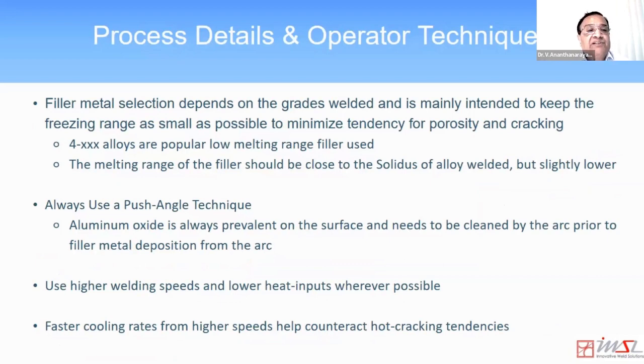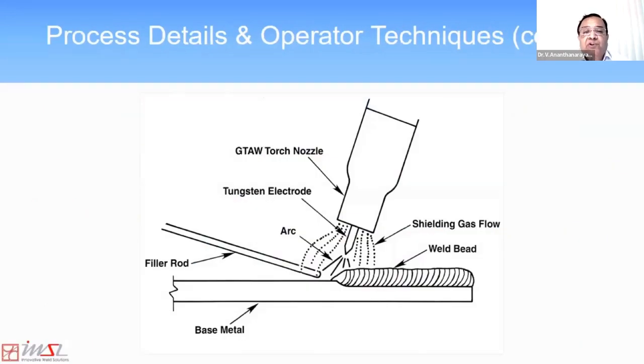And while welding aluminum, it is always necessary to use a push angle technique. A pull angle technique does not work with aluminum because of the oxide issue that I talked about. There is a need for the plasma to clean the metal ahead of the arc as you proceed. So a push angle is always essential, whether you do gas tungsten arc welding or gas metal arc welding, and use higher welding speeds and lower heat inputs wherever possible. And faster cooling rates from higher speeds help counteract hot cracking tendencies as well. And I show the push angle here that is commonly used with MIG welding or TIG welding of aluminum.